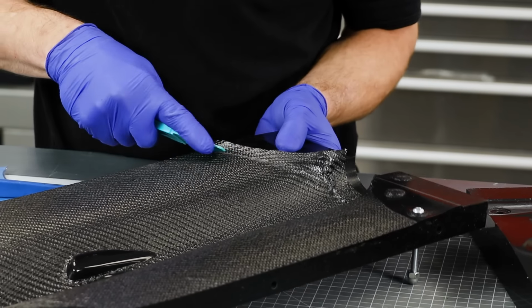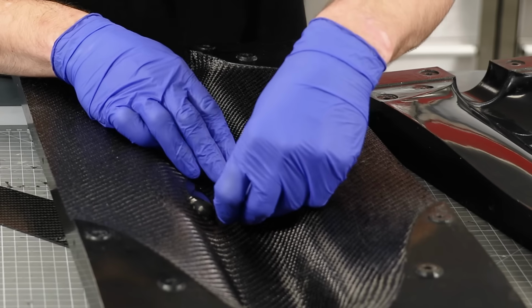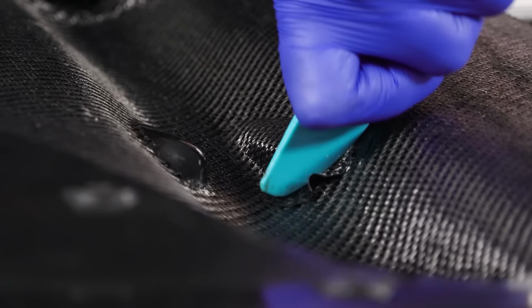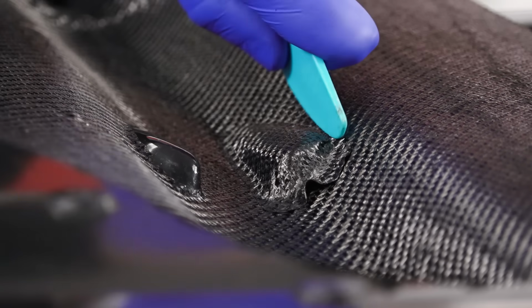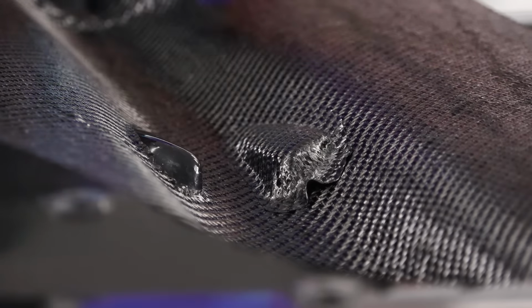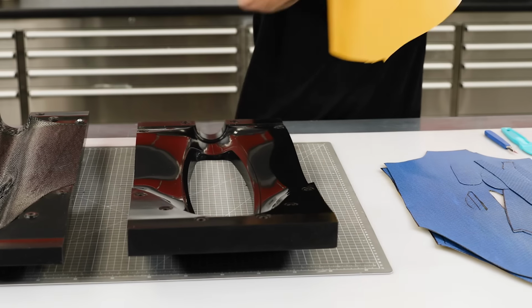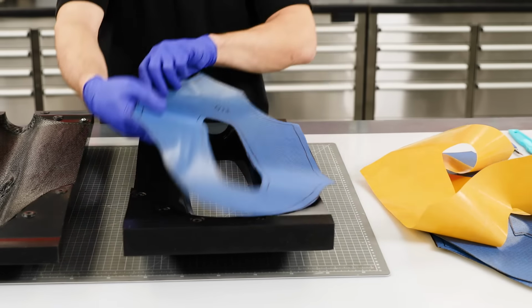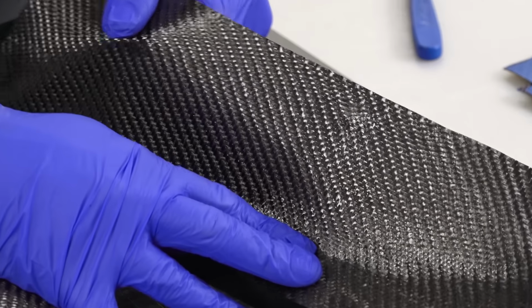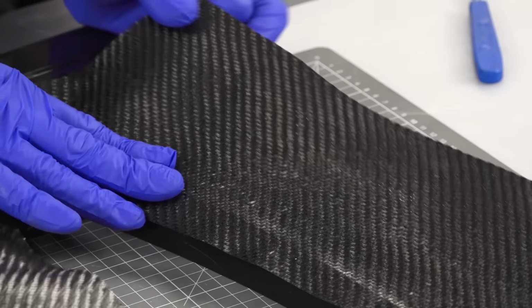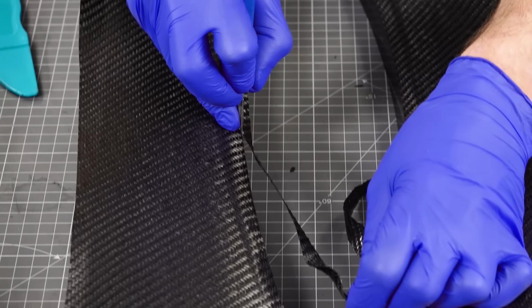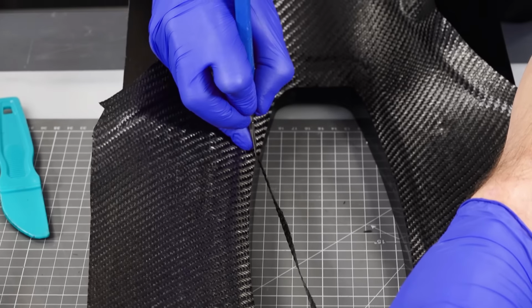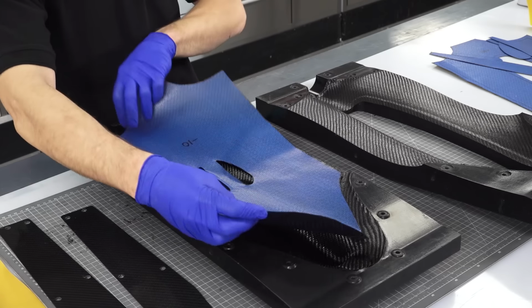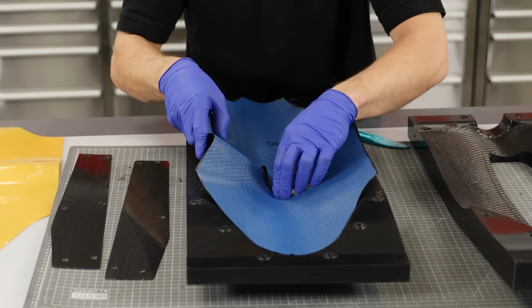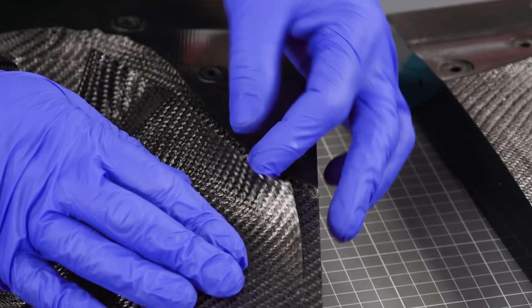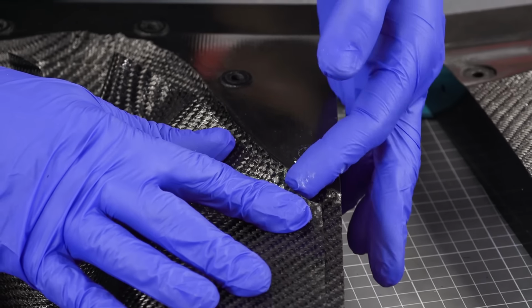As with any layup, great care is taken to ensure that the material is pressed down into all of the details and follows the mould's contours and surfaces as closely as possible. Now onto the upper surface, the first ply is laminated and trimmed back to the parting line in the same way as we did on the lower one. Back onto the lower surface, the second ply is now added. This time it stops 10 mm short of the parting line.